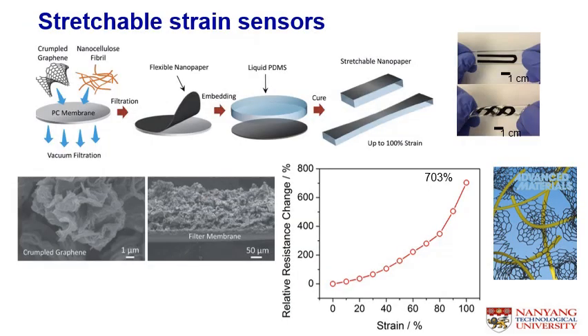In one of our earlier work in realizing strain sensors, we have utilized crumpled graphene as the sensing material, incorporating cellulose fibril that serves to improve the mechanical property. Through a vacuum filtration method, a flexible nanopaper is formed that can be embedded into liquid PDMS that realize a stretchable nanopaper upon curing that allows the stretchability up to 100% strain. The piezoresistive sensing is demonstrated here, where the change in resistance can be measured systematically as a function of strain.